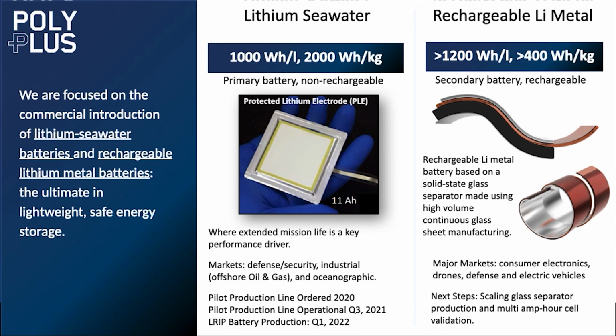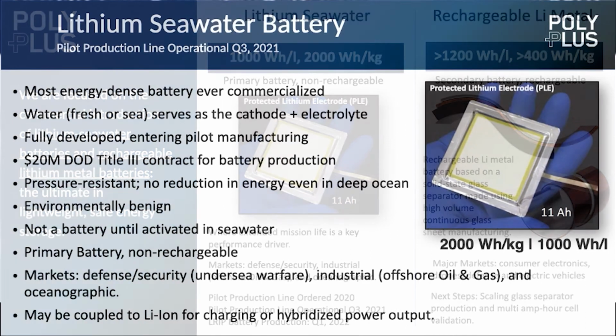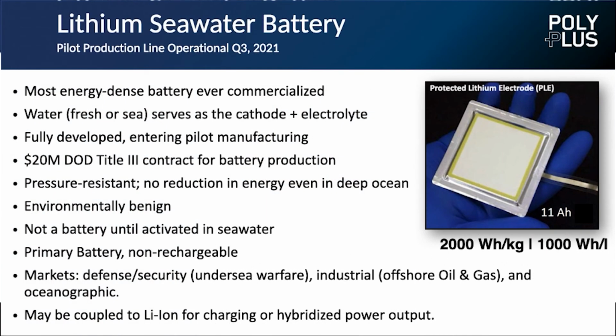So on the left-hand side, you see here lithium seawater. That is about to go commercial. But a big focus of Polyplus is developing rechargeable lithium metal batteries, and that's based on glass. And so we'll get into that in a second, how we do that. If you look at lithium seawater batteries, as I mentioned, they are very high energy density, and they're very safe because they're not batteries until they're immersed in water. So in fact, on land, they're not batteries, right? You could crush them and effectively nothing happens. They're also environmentally benign, so they're really remarkable systems, which is why, of course, we're about to commercialize these systems.